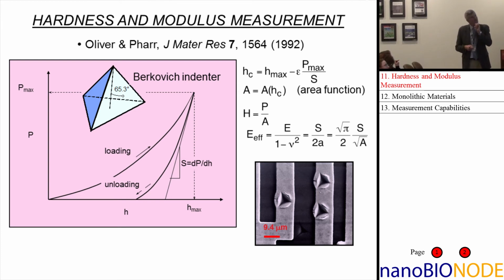of equations. That the contact depth can be determined from 3 measured parameters. Those are the maximum depth of penetration, the maximum load of penetration, and the measured unloading stiffness. Those are all measurable quantities. That the contact depth is given by those three parameters, a geometric constant, which we think is close to 0.75 for reasons that we can talk about later. And that gives us the depth along which contact is made between the indenter and the specimen. Now, that works in about 90% of the cases, but it doesn't work in 10% of the cases.